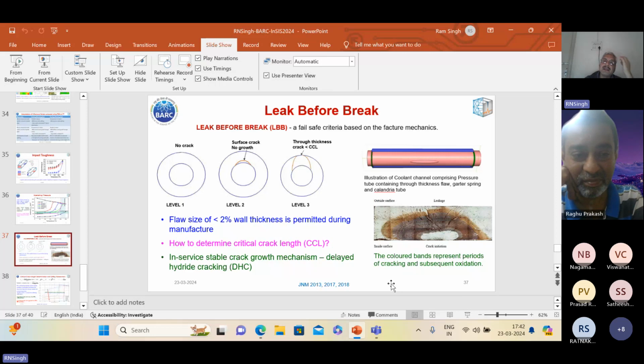What they have done is they have tried to marry FEM simulation with phase field modeling. We are also working with Professor Rajgopalan from IIT Hyderabad on a project where we intend to model this DHC phenomenon, again using phase field simulation and FEM simulation. There, a lot of material property parameters are not very easy to get, and whenever you do modeling work, if those parameters are not explicitly determinable, they become fitting parameters. So at least we are trying to model just the DHC part itself, which is under a static loading. Cyclic loading we have not ventured into, because even this DHC part is not yet fully modeled.